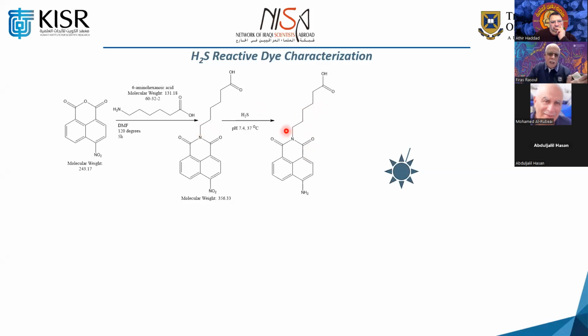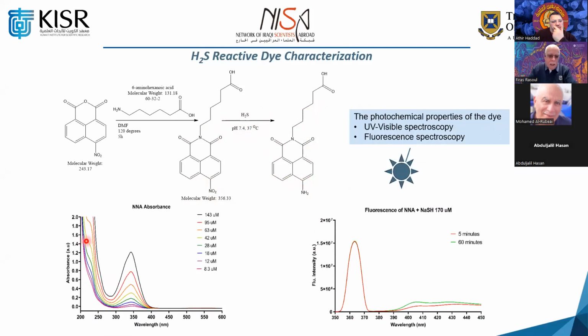Before we couple it to it, we really need to evaluate this. So what we did was at pH 7.4, 37 degrees centigrade, even though the temperature in the oil field is quite high. And we reacted it with H2S, and you find it easy to convert the NO2 to NH2. And of course, the material goes from non-fluorescent to fluorescent. And you could see here the absorption at different levels. And then here is the fluorescence, which is a broad peak. Exposure for 60 minutes and exposure for 5 minutes. But if you leave it longer, of course, you improve on that. But again, you need to optimize what you are really looking for.